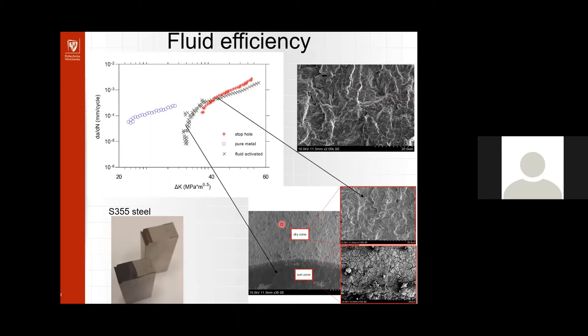In the microscopic view from scanning electron microscopy fractography study, we can see the 'wet zone' — the zone where the fluid was activated. When the fluid dries, the crack starts to grow in its normal direction. From the microscopic point of view, this phenomenon could be observed on the crack surface. Together with Professor Nykyforchyn, we called this phenomenon 'artificial crack closure.' The typical crack driving force was decreased, which was the result of the crack deceleration method.